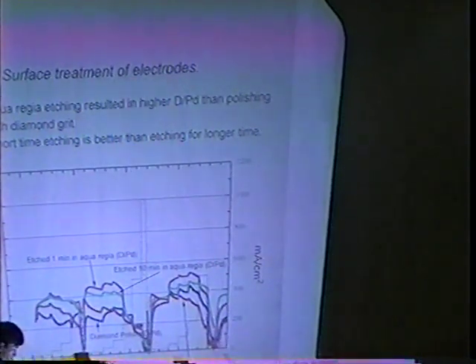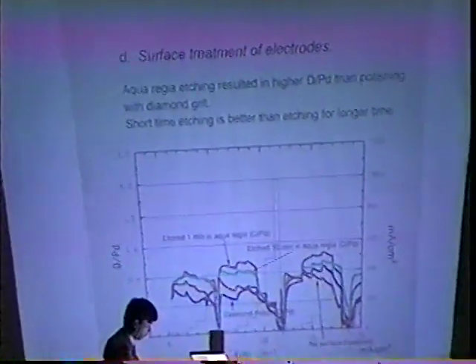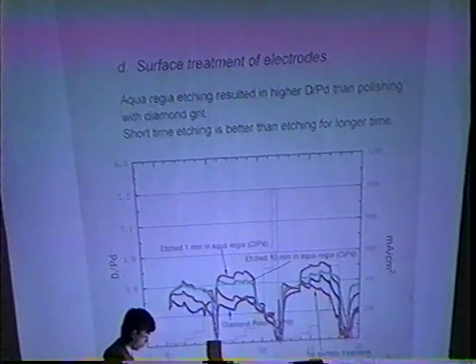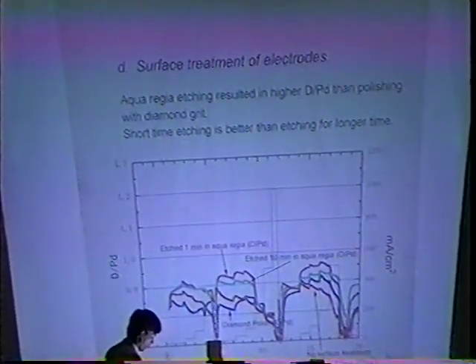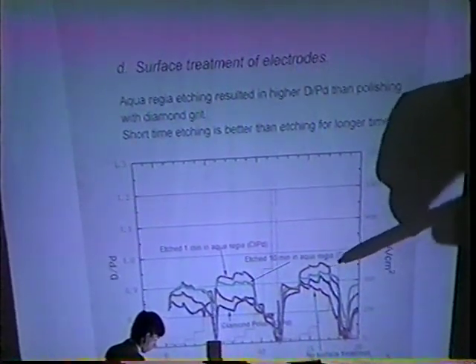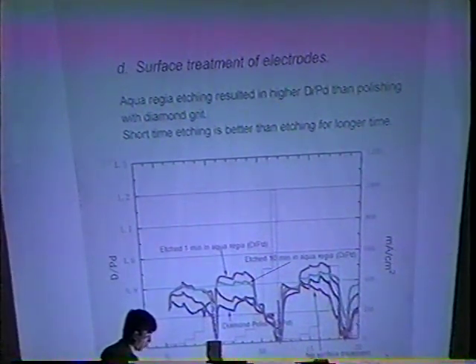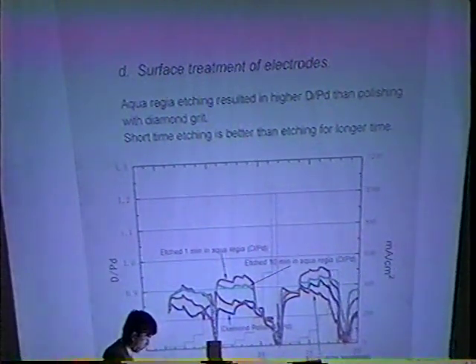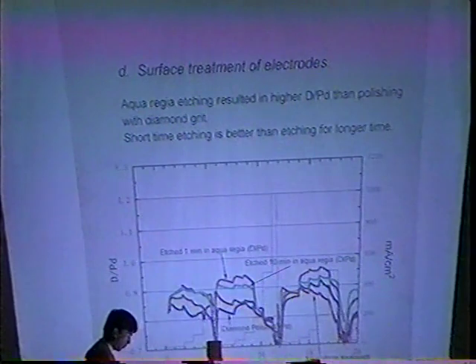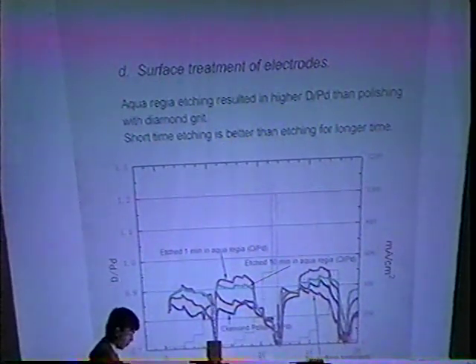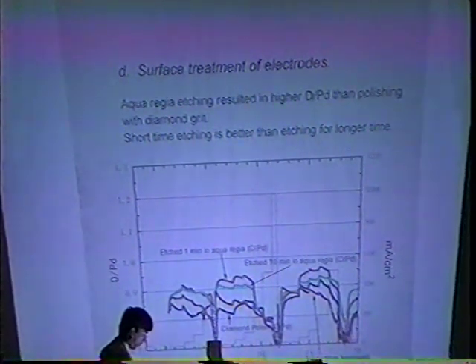This shows the effect of different surface treatments upon the D/Pd ratio. The treatments include polishing with diamond grit and etching with aqua regia for different lengths of time. Cathodes etched with aqua regia show the higher D/Pd ratio, 0.95, than cathodes polished with diamond grit, 0.94, and 0.92. The surface treatment of electrodes was also observed to have an important effect. For example, etching the cathode in aqua regia results in higher loading than polishing with diamond grit. Also, short etching time appears to be better than etching for a long time.